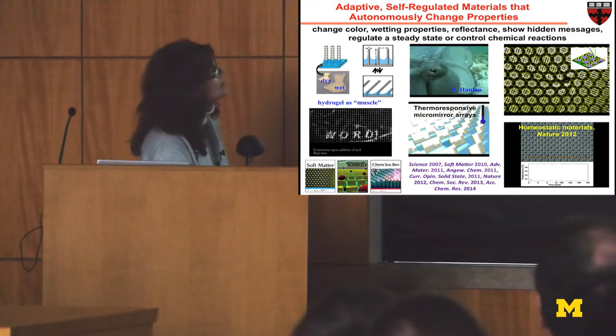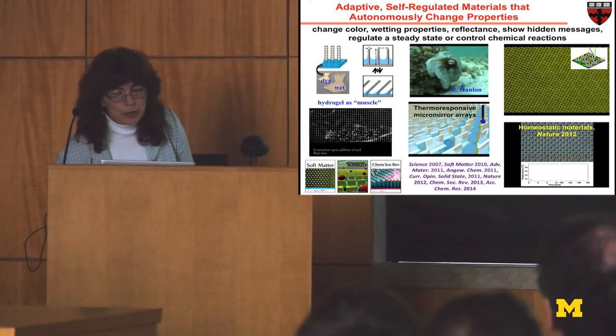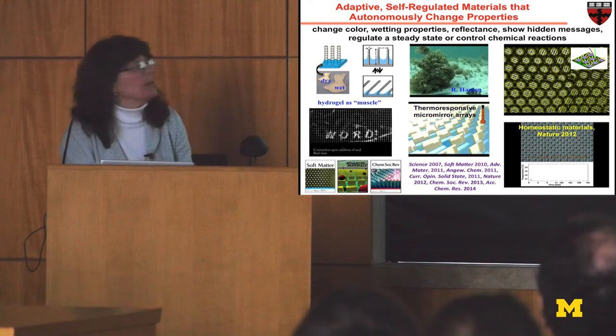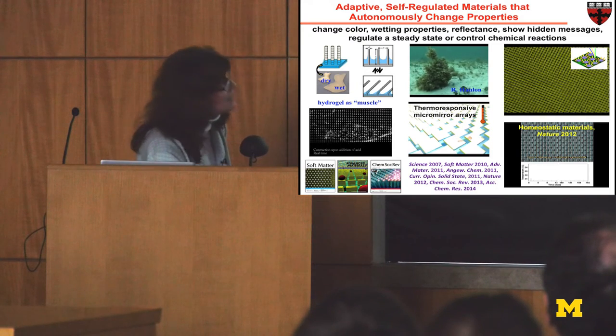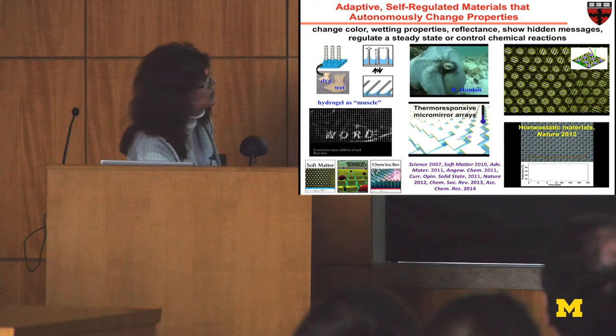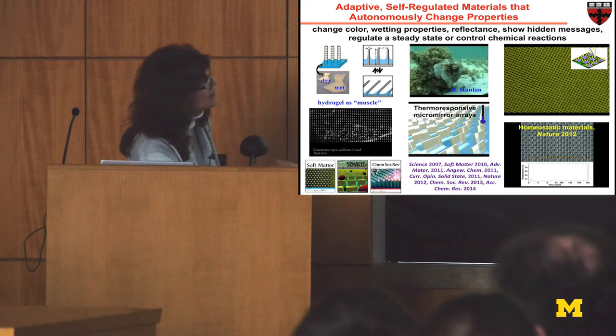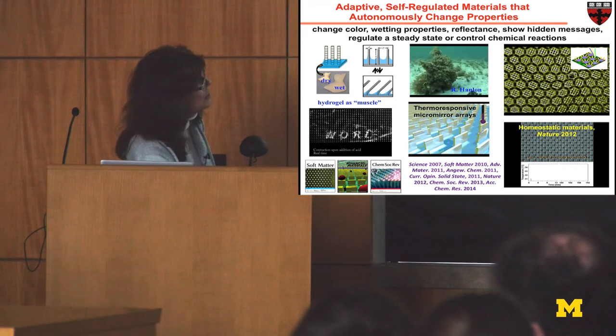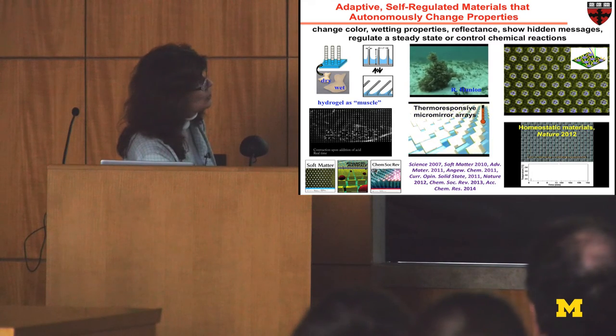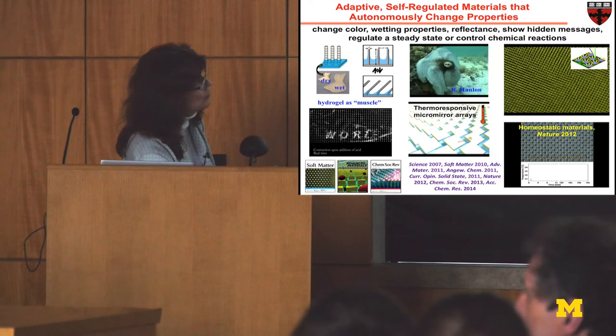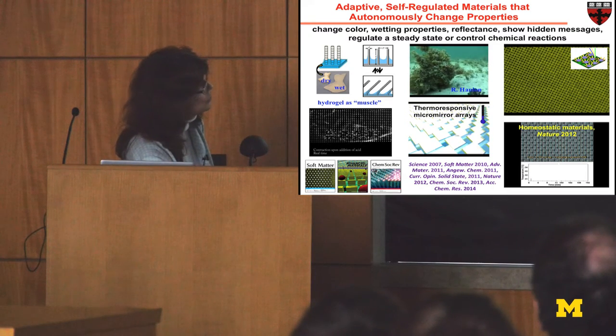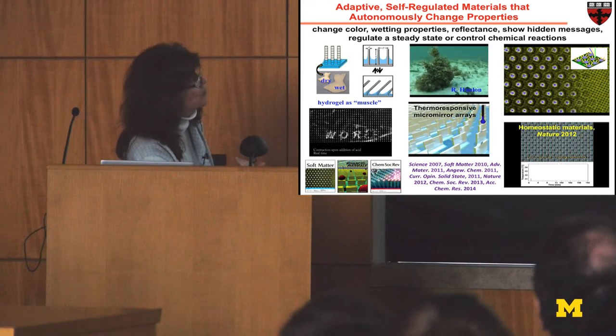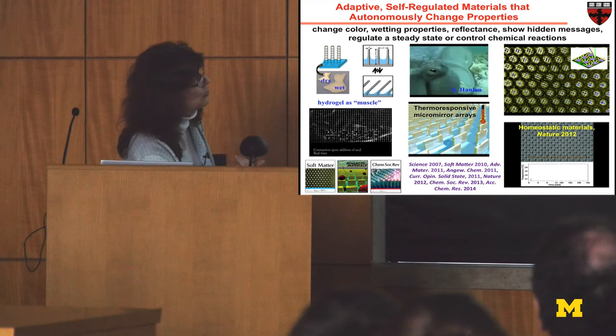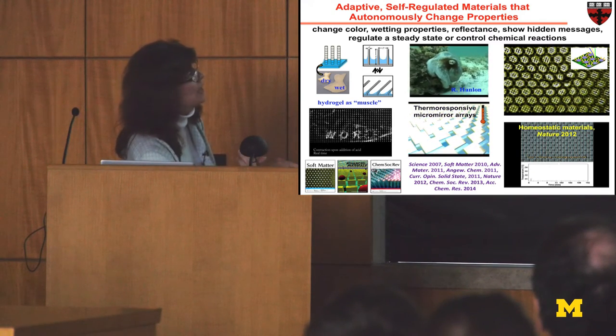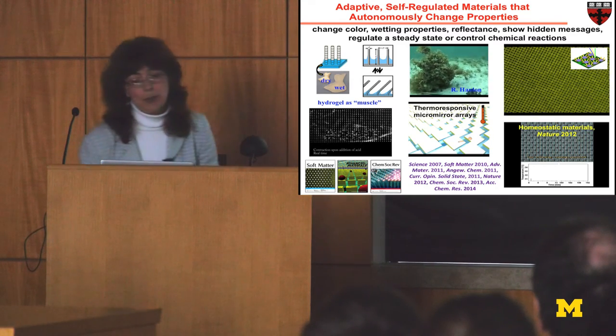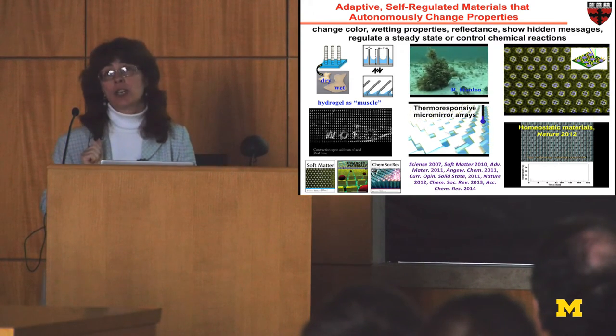There's yet another system that decided to make it in a homeostatic material that keeps a steady state. It holds the temperature steady in the system because it is designed in such a way that it produces heat up to the level that the gel contracts. It contracts, nothing can be done when they are far away from the chemical reaction. It cools to a certain temperature, it has to stand up again, and it oscillates in this way, keeping the temperature in the narrow range defined by the gel that you use.